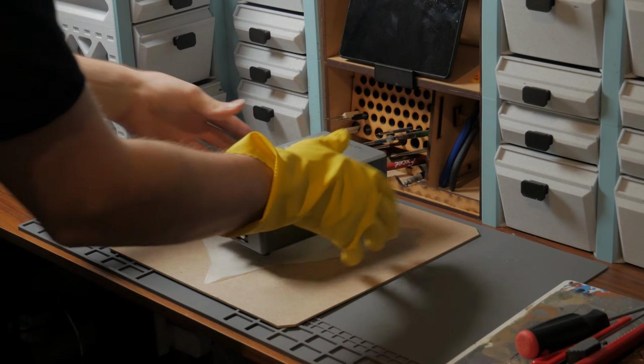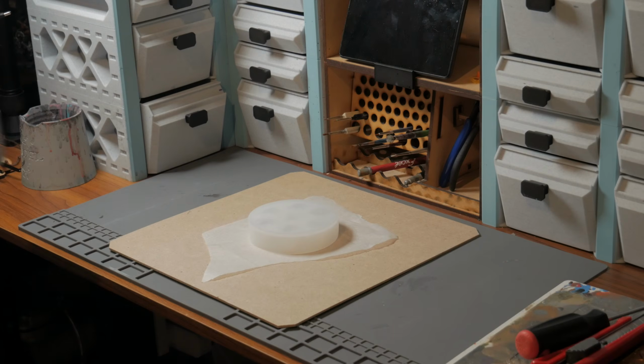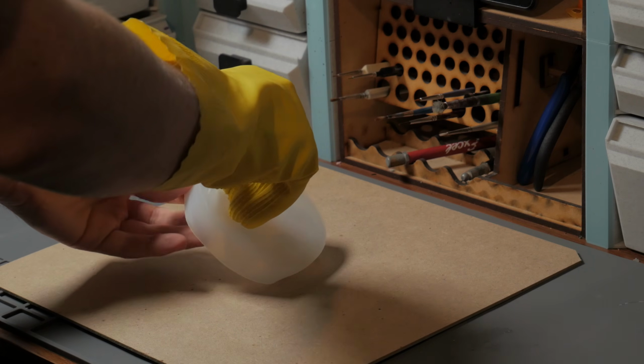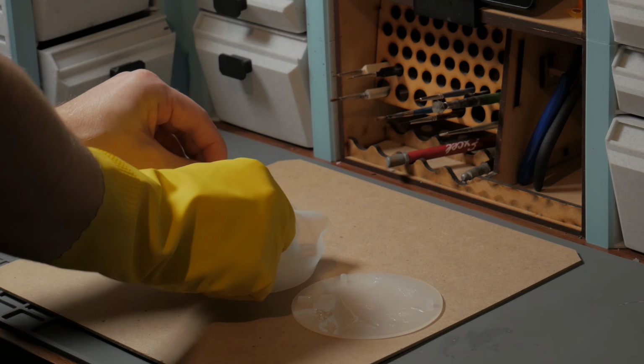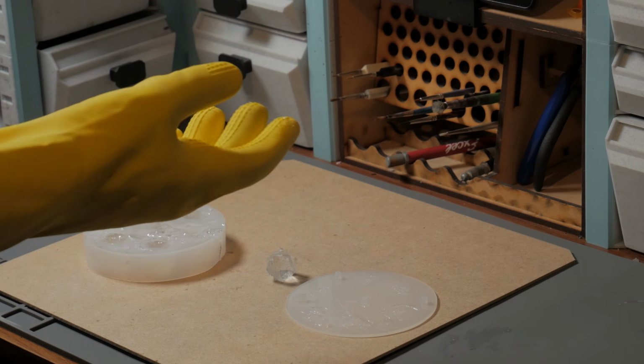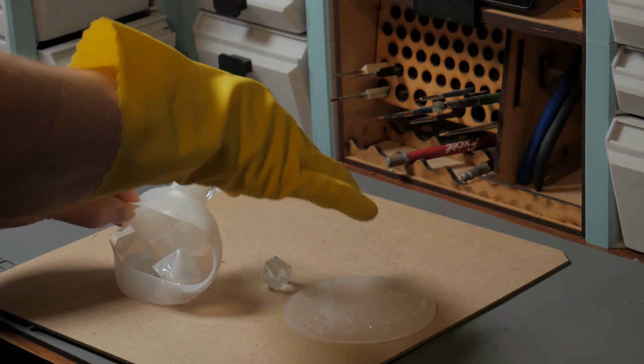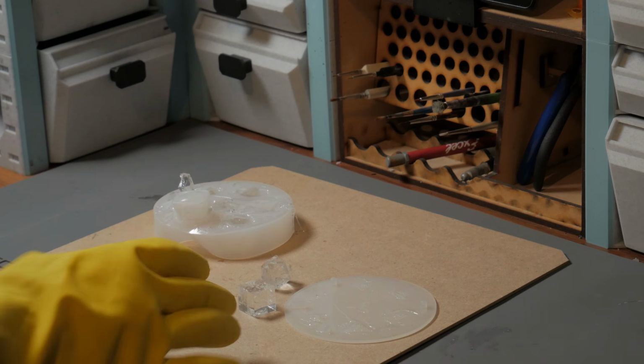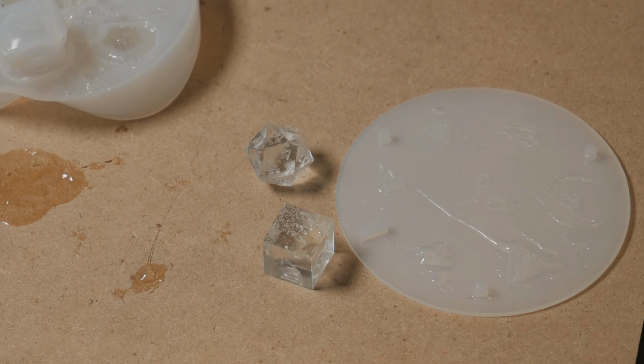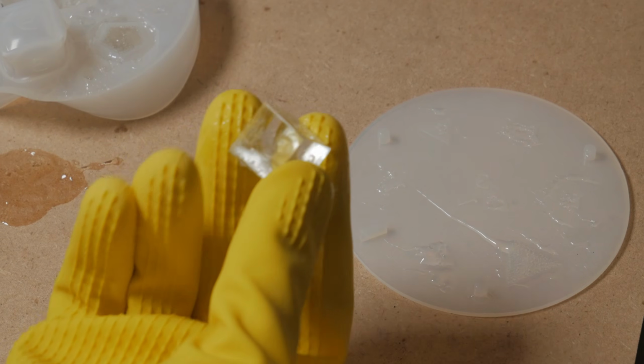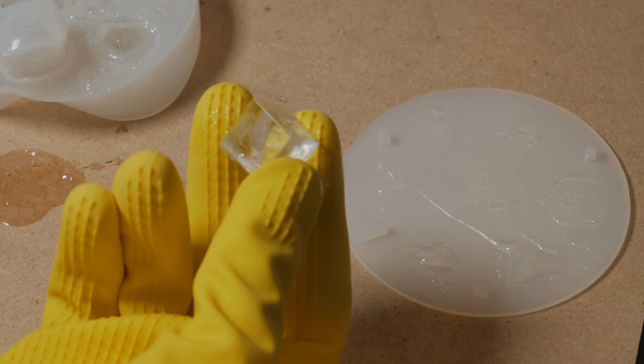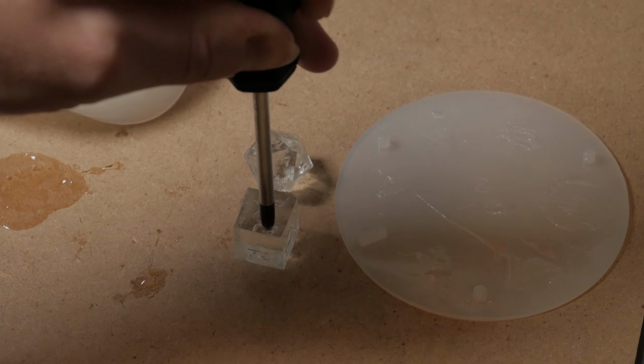And oh, how wrong I was. I don't know if I didn't mix this resin well enough, had it somewhere too hot or too cold, or somehow messed up the ratios, but this did not work. Some of the dice were mostly cured, but had a sticky top layer that refused to cure properly, and overall these dice were super soft. A couple of them were even straight up still liquid resin. So this batch of dice and the mold were a complete write-off.